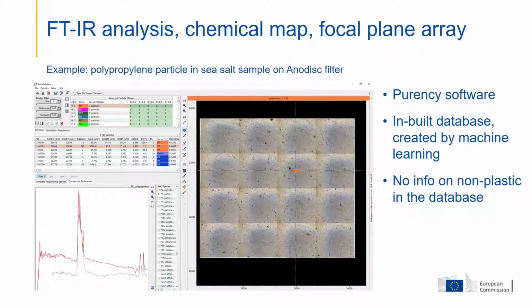In this case, we find results very similar to the Raman, which was basically that there were very, very few polymer particles in proportion to the number of inorganic materials. In reality, we only found a very small single-digit number of polymer particles amongst many hundreds of particles actually analysed.